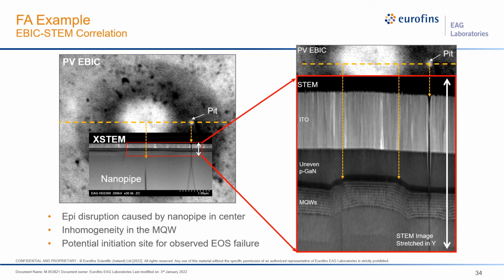And so if we can then take this STEM data and correspond it to the EBIC data we have now, we can actually look and see how this EBIC data relates to what's going on in the sample. And so if we take this region here in the red box and stretch it in the Y direction, we can exacerbate what's going on in these thinner layers, and we can really see this massive multi-quantum well disruption that's occurring here. And so now we can really understand why the EBIC signal is brighter in the center. It's because our active layers are actually closer to the surface than on either side of it. And in fact, it's darker on either side because they end up being further away here and then heading back towards the surface again. So now the EBIC signature really makes sense.